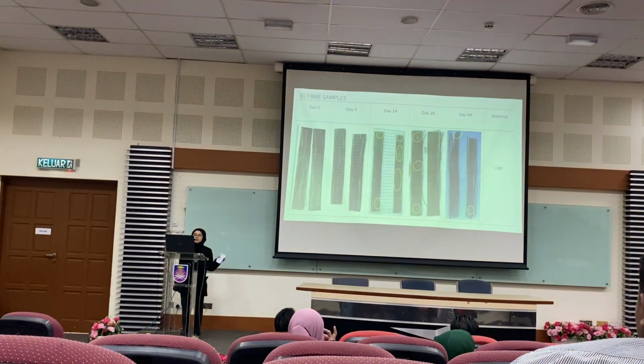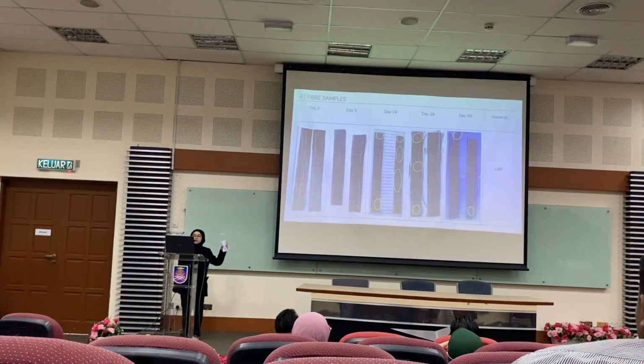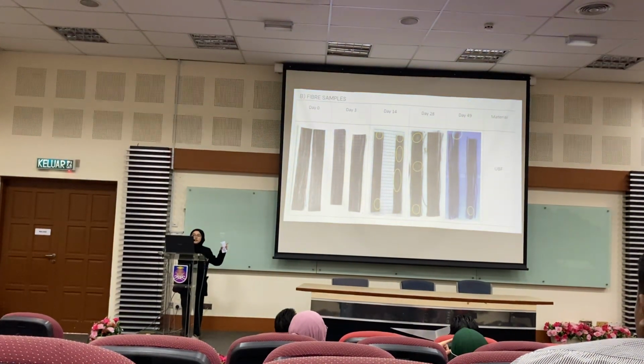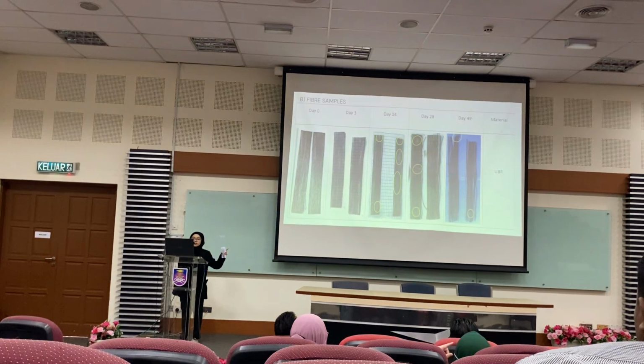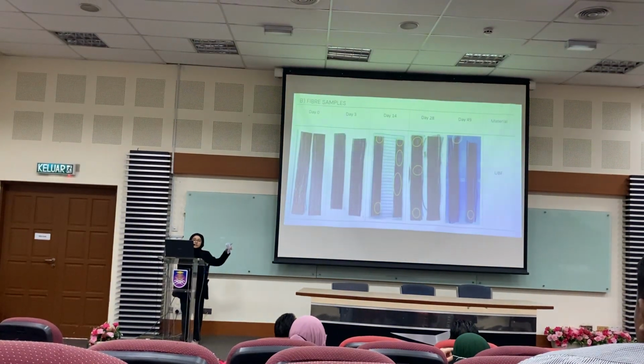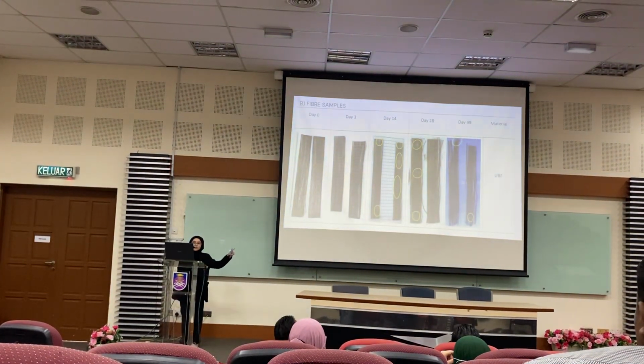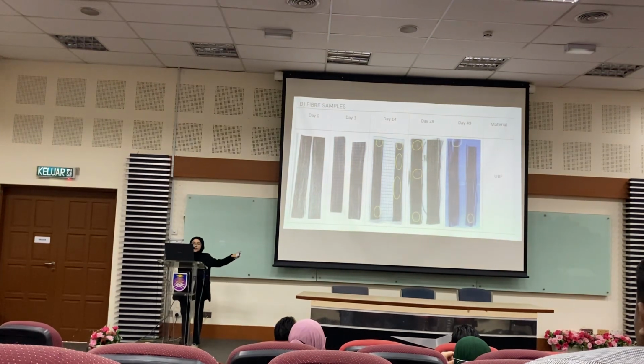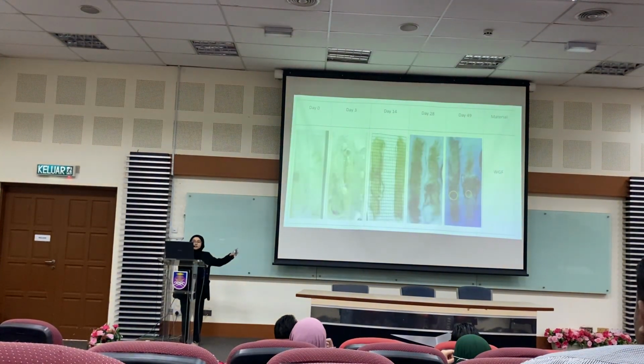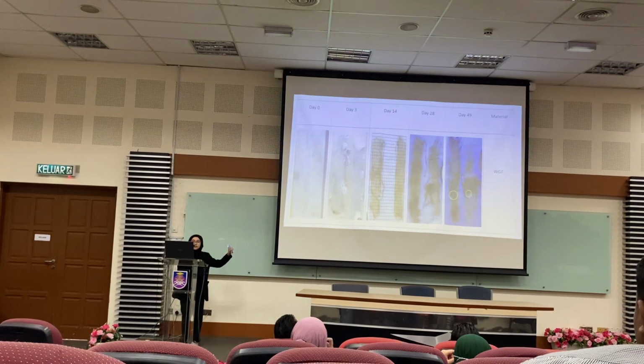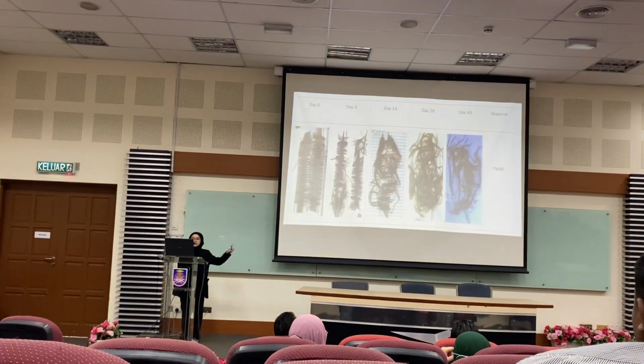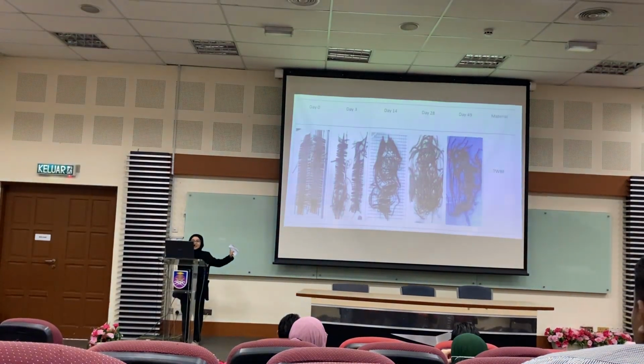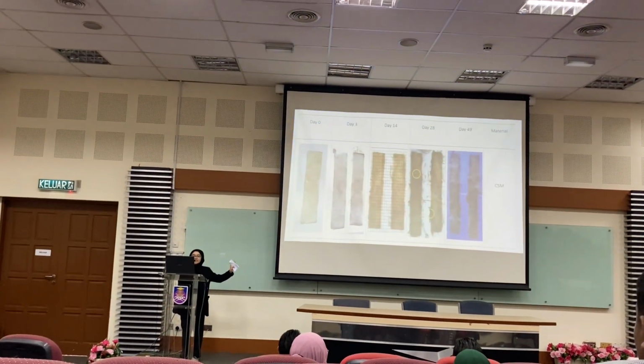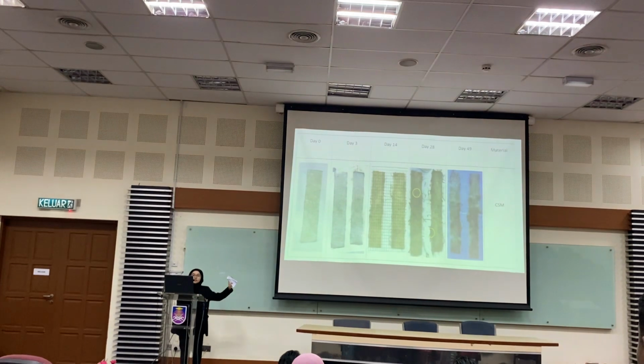So here are the fiber samples. The yellow circles circle the visible biofouling that can be seen on the fibers. As you can see, on day 14 there is a lot of biofouling, but it decreases by day 28 and day 49 for UBF. For WGF, there is biofouling on day 49. For TWBF, as you can see from the condition, I will explain. And for CSM, there was only biofouling on day 28.